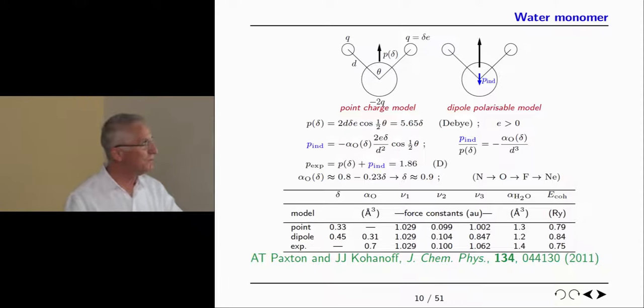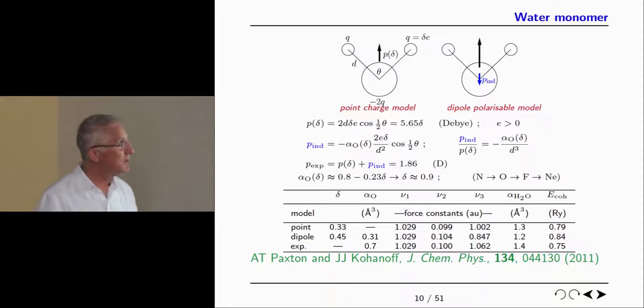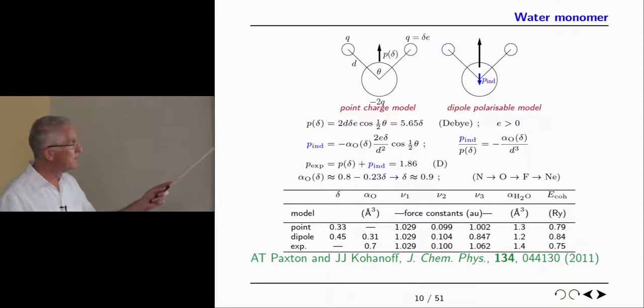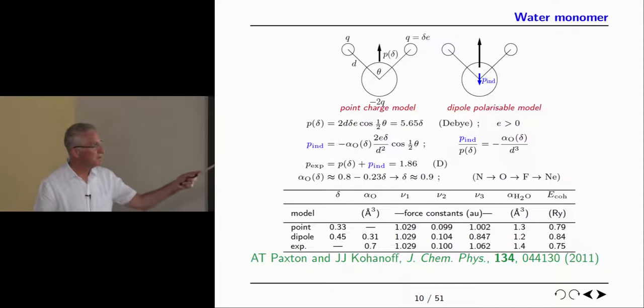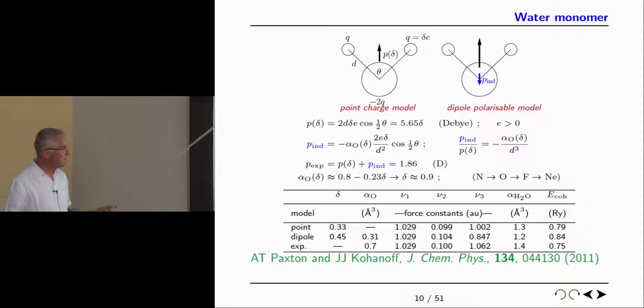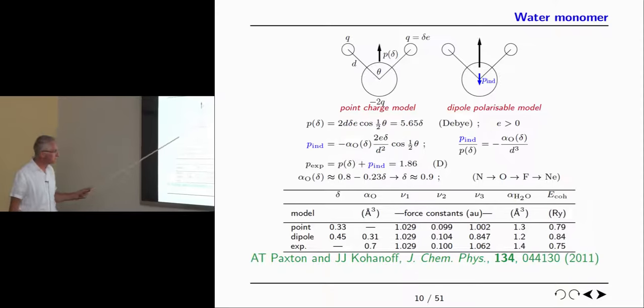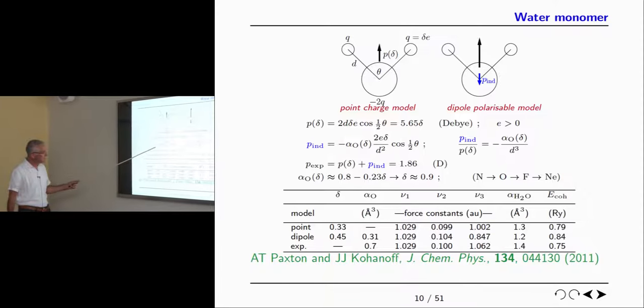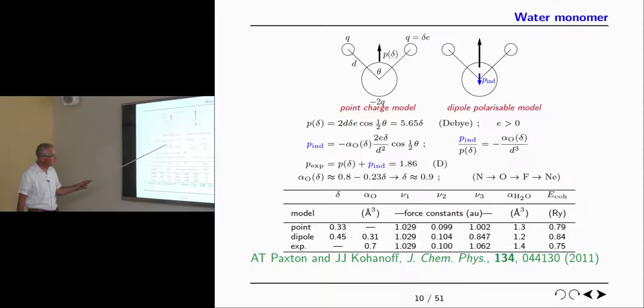But if you're thinking about going beyond the point charge model, say to the dipole level, then the charges on the two hydrogen atoms induce an electric field at the oxygen nucleus, and that electric field will act to polarize the oxygen atom. So there's an induced dipole moment, it points in the opposite direction, that's this blue thing, and it's simply the polarizability of the oxygen anion times the electric field. Now the polarizability of the oxygen anion may well depend on delta, because it may depend on its charge state. The oxygen 2 minus ion will have a different polarizability than, say, the oxygen 1 minus. So this would be a sort of self-consistent formula.